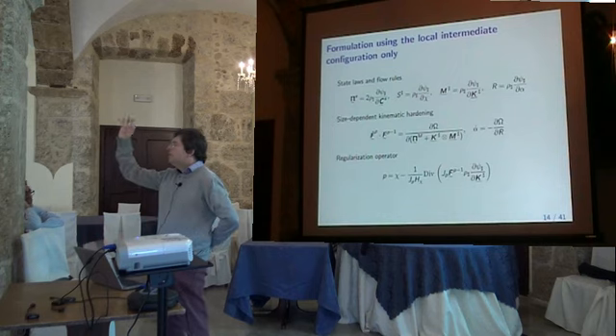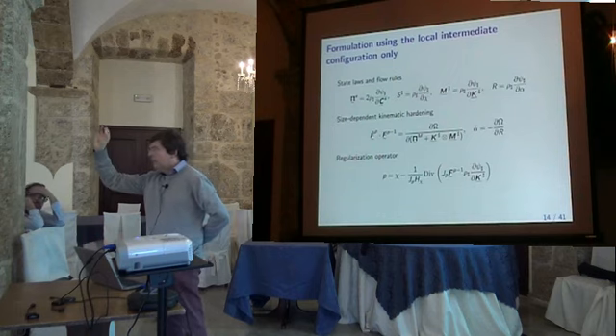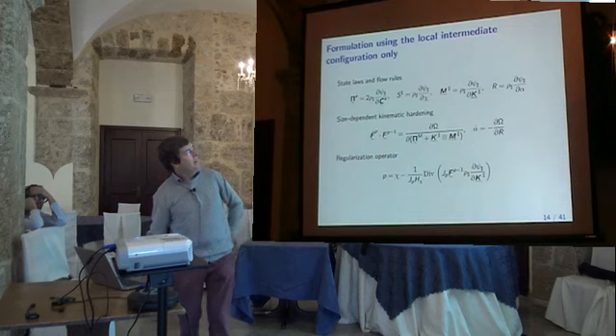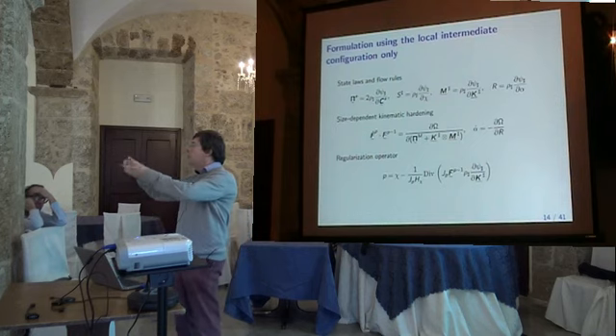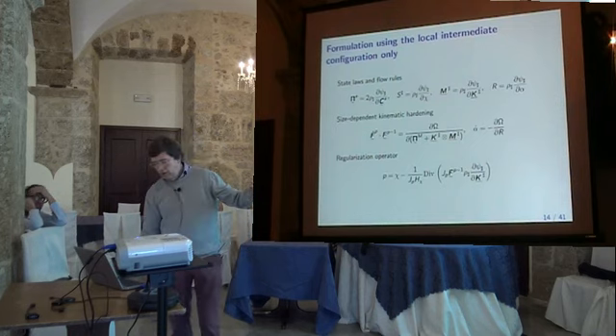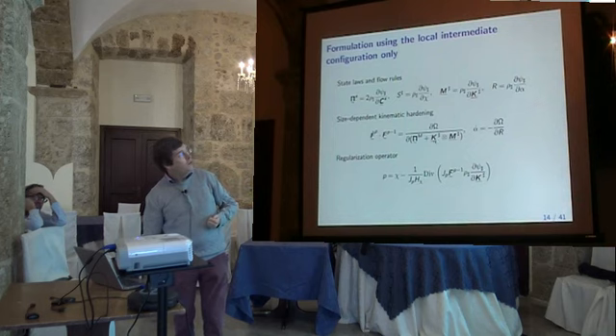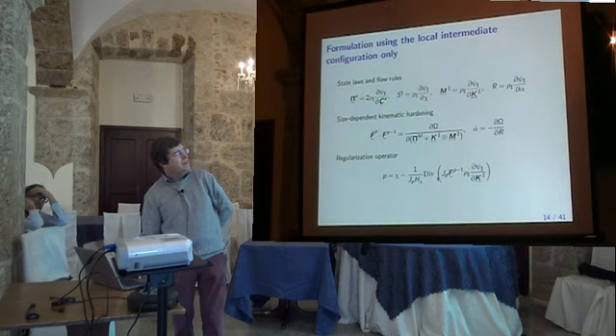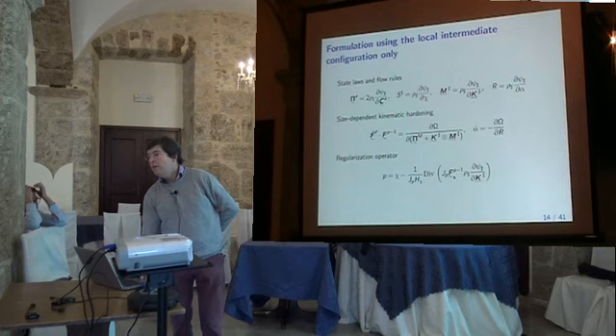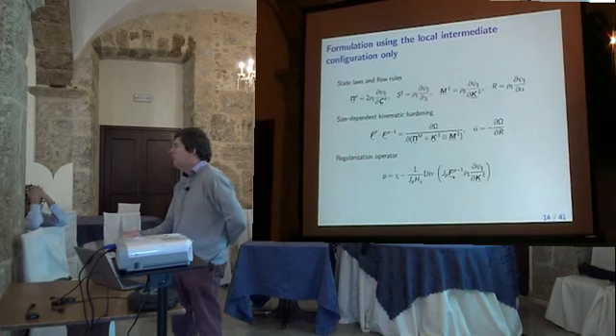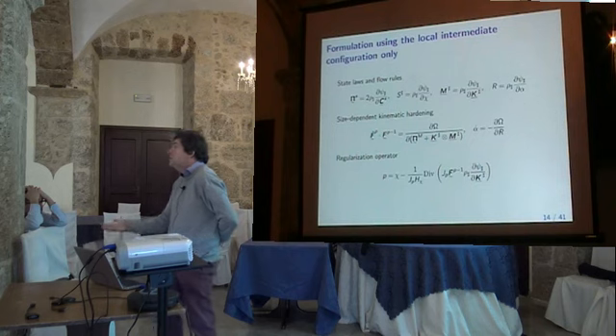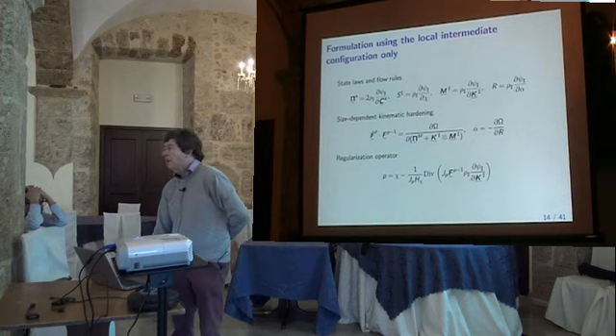So you see that in the previous case, I had some effect on a scalar function, but here you end up with an effect on the stress tensor. And this is a kinematic hardening. And you see the equation is not a Laplace anymore because you cannot distribute the divergence on the gradient here, because you have the FP which is there. So this is a complex regularization equation. We don't even know if it's good for simulation, but this is what you get.